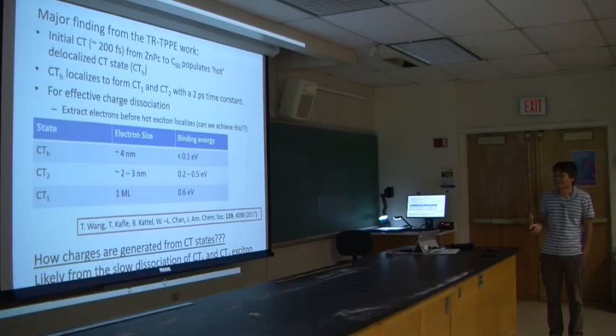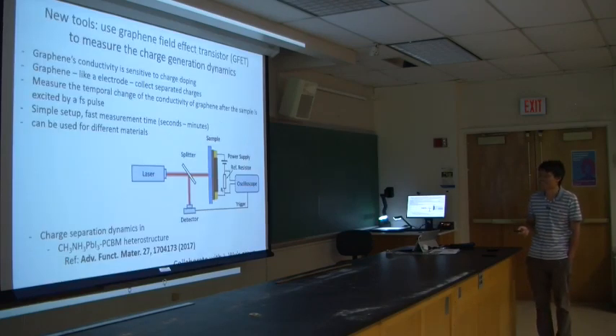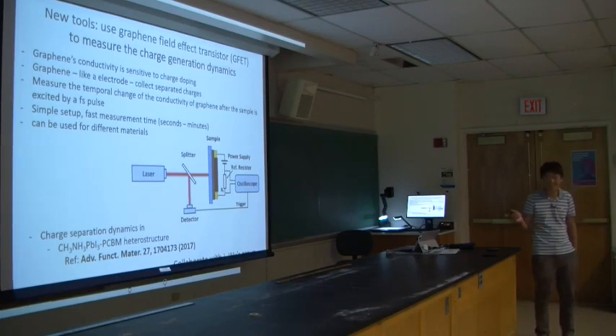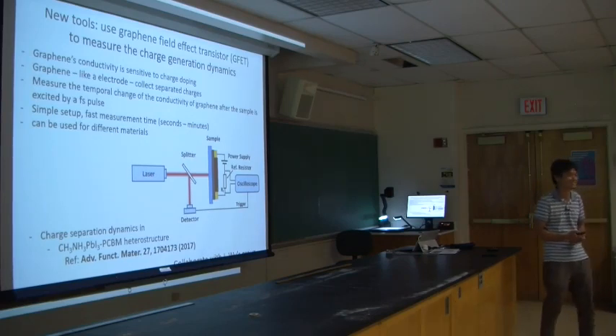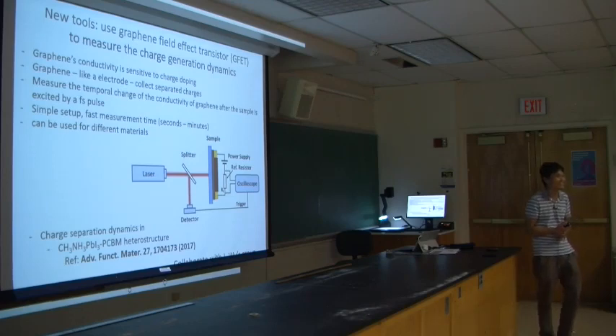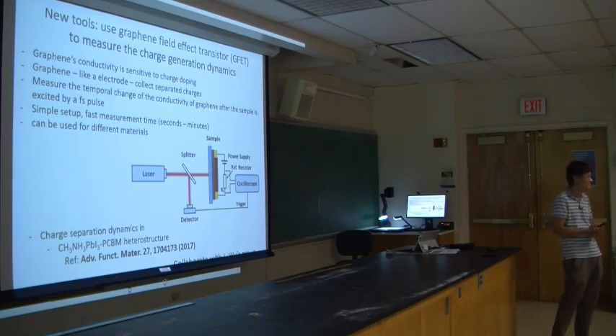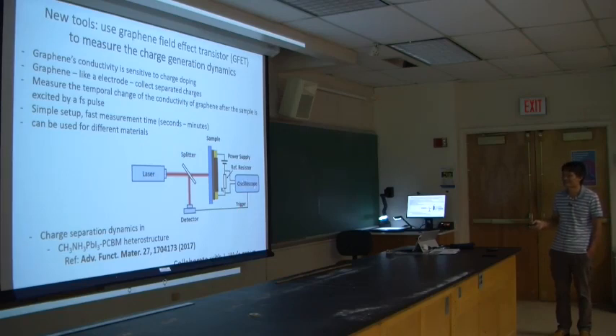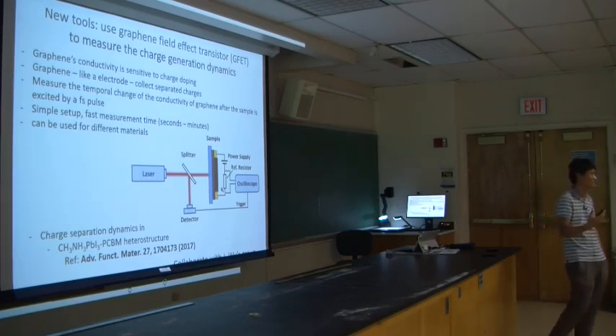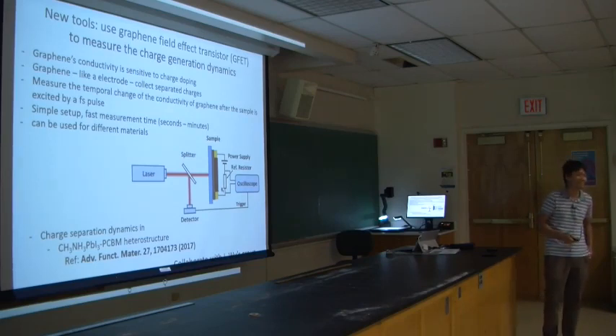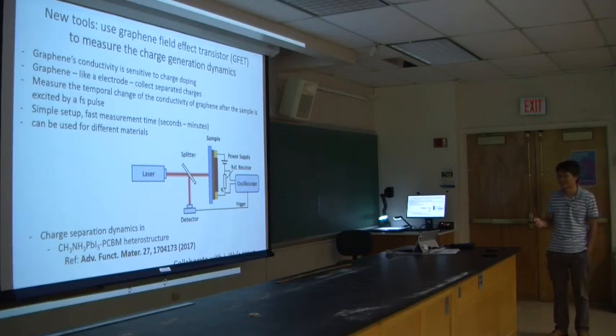Anyway, we are also interested in whether free carriers are actually generated from this charge transfer exciton. It's a little bit sidetracked here. We collaborate with Judy's group, which is very good at making graphene field effect transistors. It turns out they are really good light sensors. We use those sensors to probe the free carriers generated by these charge transfer excitons. The probe is a little different: we probe the electrical signal, so we don't have as good time resolution, but we can probe free carriers quite exclusively, because you can only probe free carriers with this kind of electrical circuit.